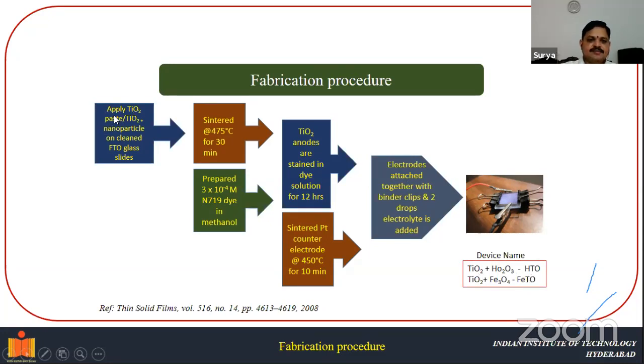Initially, you apply titanium dioxide paste on a clean FTO glass slide, then sinter at 475 degrees centigrade for 30 minutes. In parallel, you can also prepare N719 dye in methanol. The titanium dioxide anodes are stained in the dye solution for 12 hours. After sintering, keep your titanium dioxide anodes in dye for 12 hours. Then sinter the platinum counter electrodes at 450 degrees for 10 minutes.